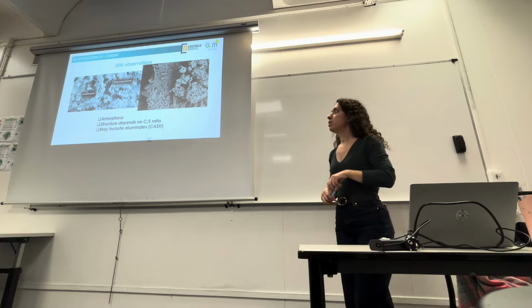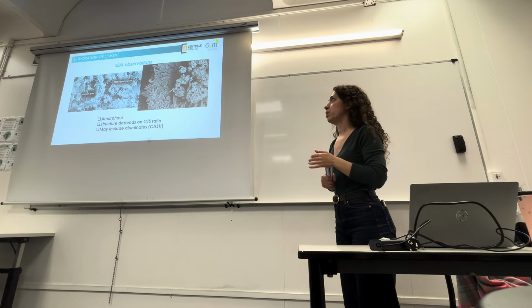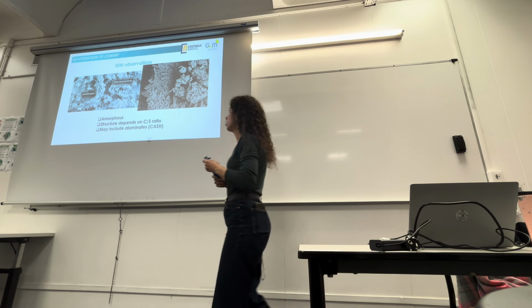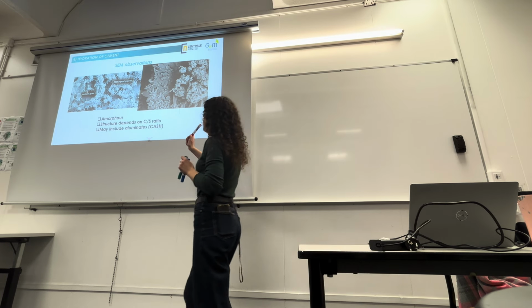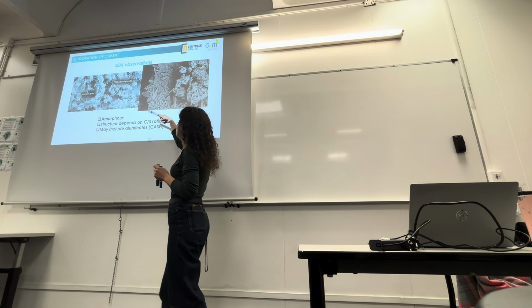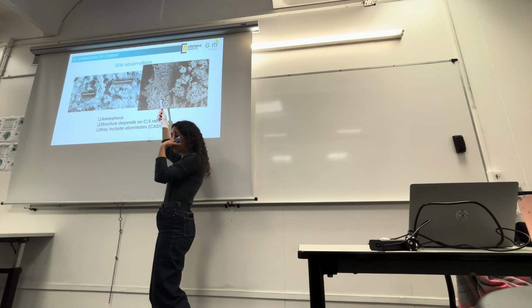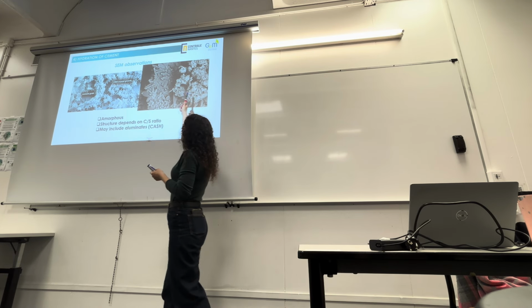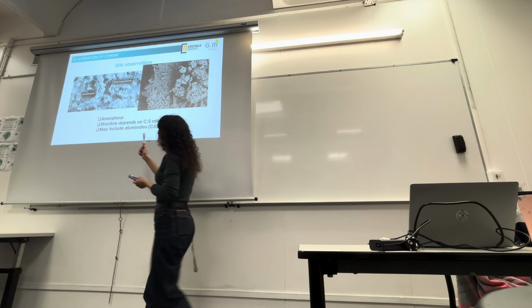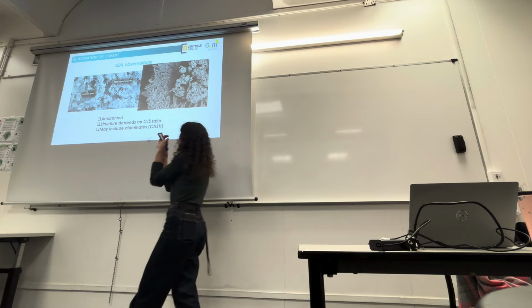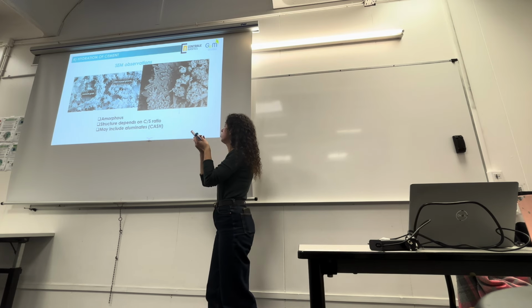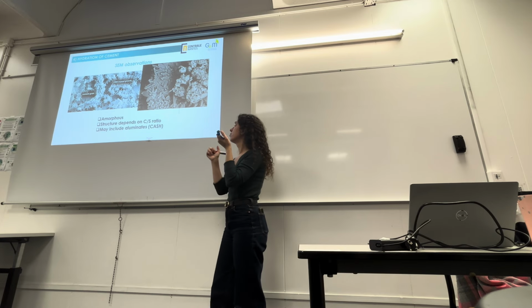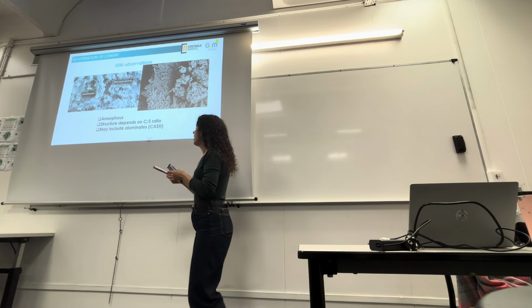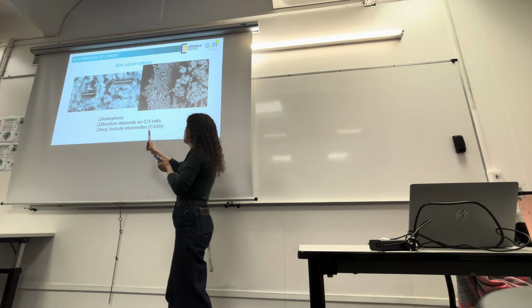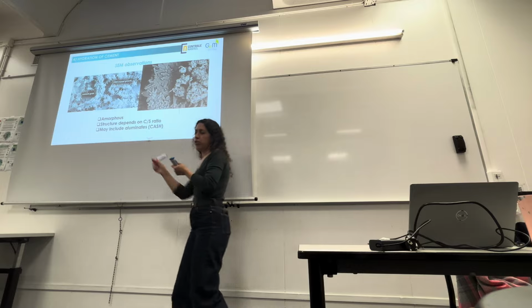So these are some scanning electron microscopy observations of CSH. So CSH, they are amorphous. So this is crystalline, this is amorphous. So this is not CSH, it is calcium carbonate. And these are CSH. You can see also here that it's not crystallized, it's roughly like an alveolar sponge. Maybe. The structure of CSH depends on the calcium silicon ratio.